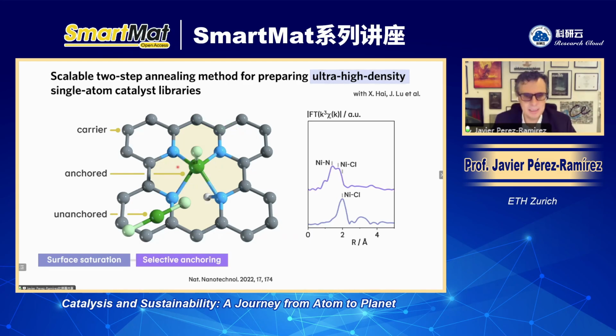That's the first step. Then the second thing we do is a second step low temperature annealing. In this low temperature annealing, what we basically do is remove some of the chlorine ligands from the nickel chloride. And upon removing some of the chlorine ligands, the nickel site will go and attach to the nitrogen functionalities on the host. You can see the catalyst at this stage still contains some chlorine, but you also see the bonding of the nickel atom to the carrier, nickel-nitrogen bonds.